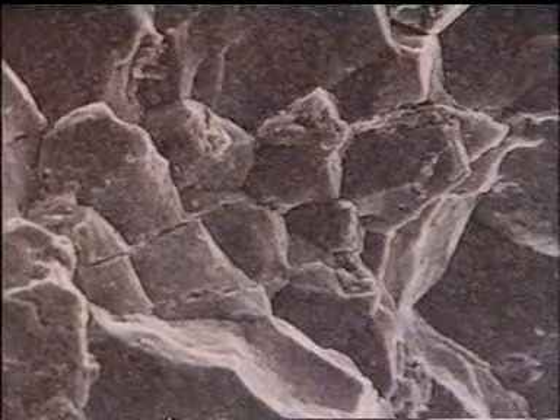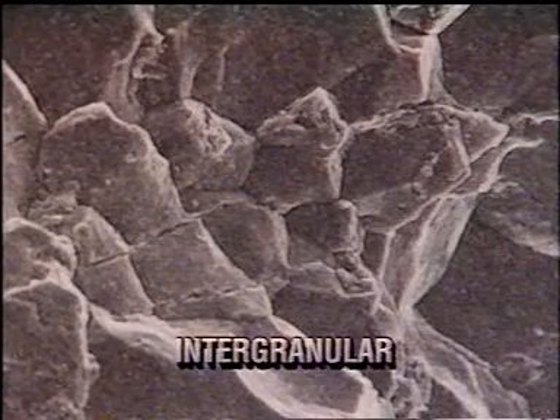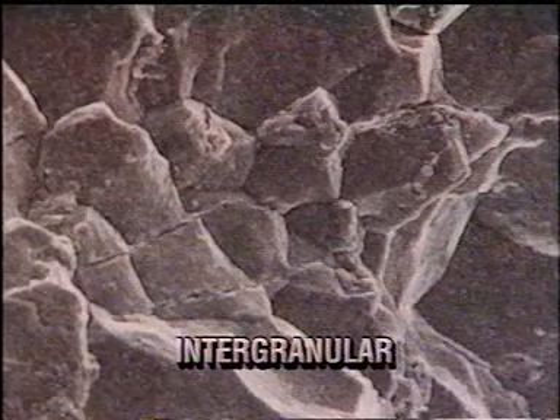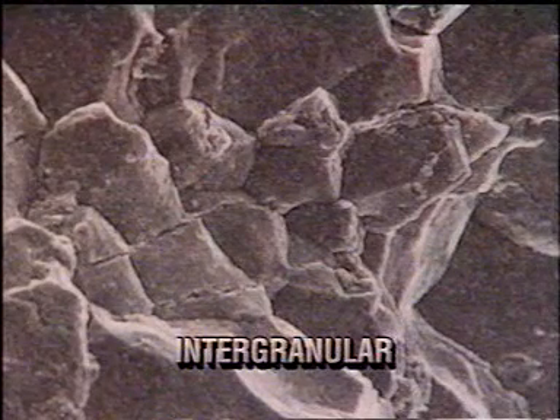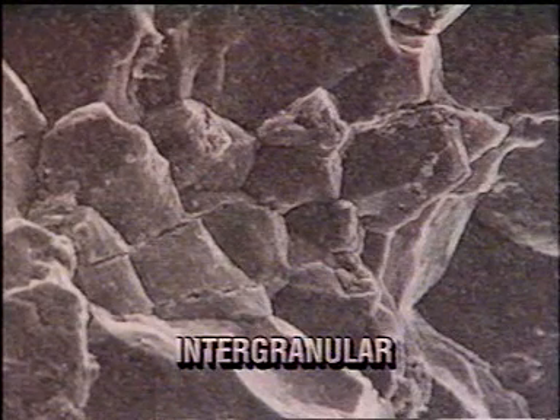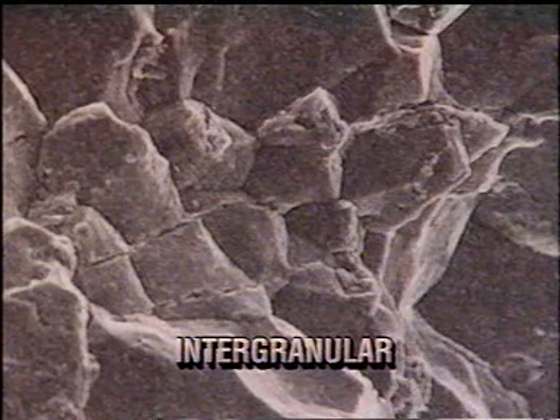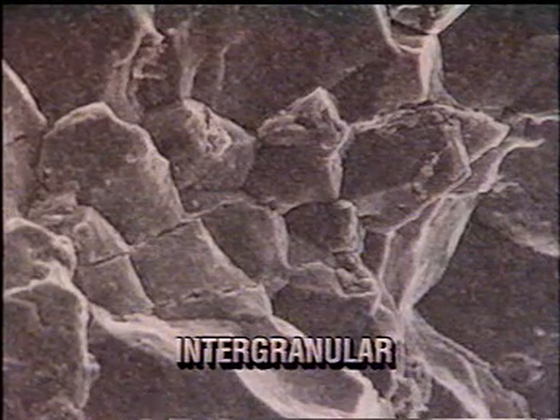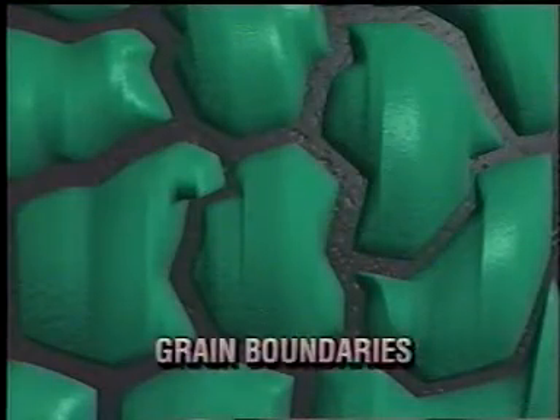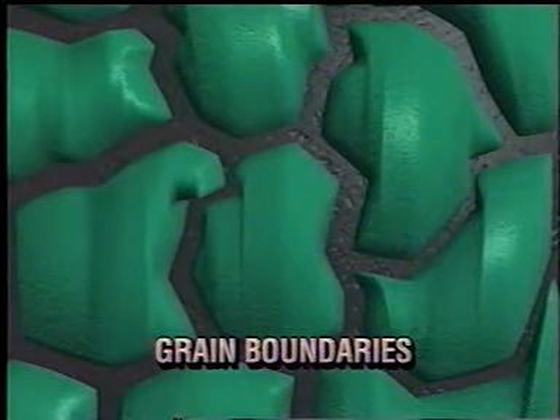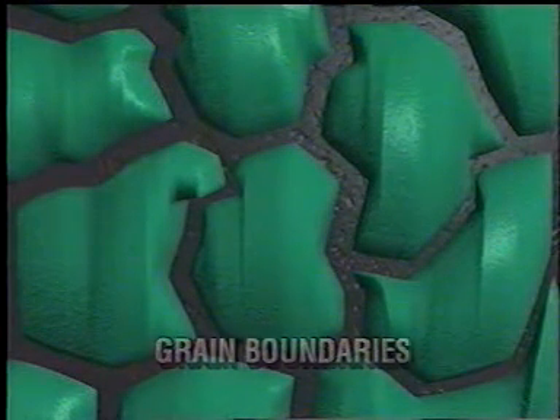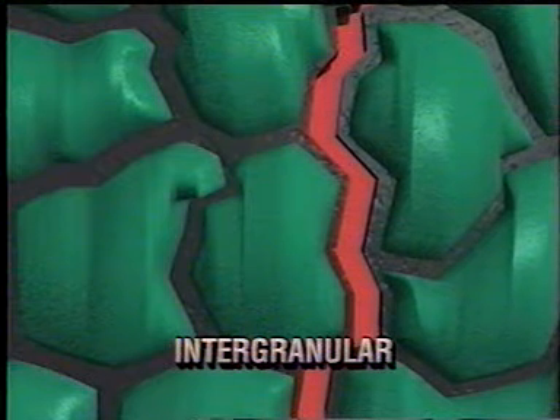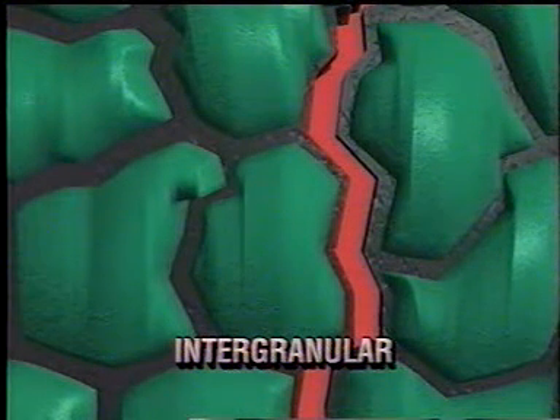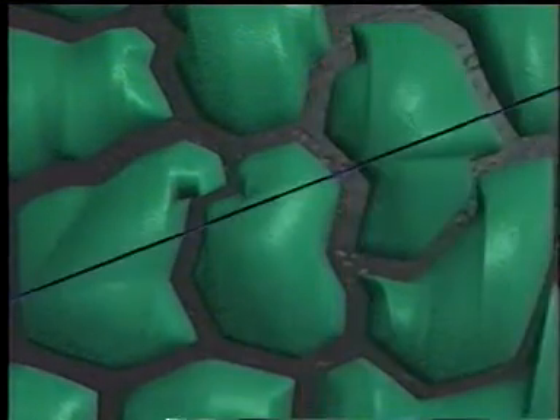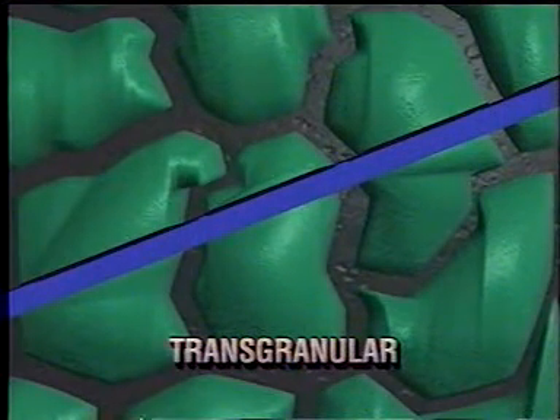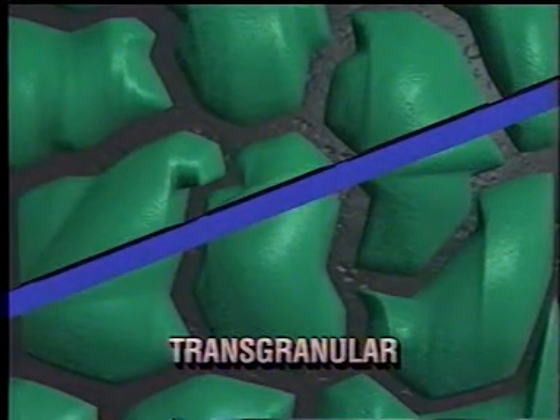The other type of brittle fracture is intergranular. Intergranular fracture occurs between the crystal grains of the metal through the grain boundaries. This is due to a variety of mechanisms that make the grain boundaries weaker than the grains themselves. The grains of a metal can be compared to bricks in a brick wall. The mortar between the bricks would represent the grain boundaries. An intergranular fracture would occur between the bricks through the mortar or the grain boundaries. A cleavage fracture, transgranular, occurs through the bricks, through the grains themselves.